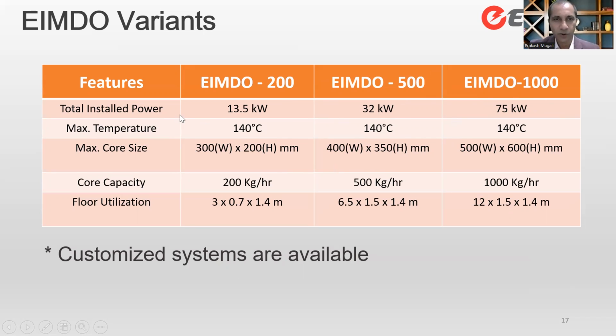And the installed power we have given is 13.5 kilowatt for the first one, 32 kilowatt for a 500 kg per hour machine, and 75 kilowatt for EIMDO 1000 kg per hour. Compared to conventional electrical dryers of the same capacity, the installed power and the consumed power is at least 25 to 30% lesser in these ovens. The operating temperatures are 140 degrees Celsius. And of course, you can see the footprint and the core capacity.